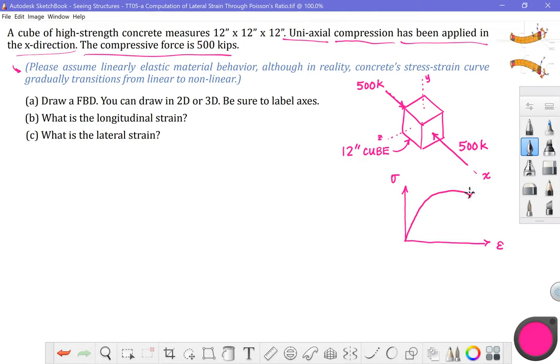something like this. So unreinforced concrete will have a linearly elastic range here at the beginning of the curve. The slope is the modulus of elasticity. And then we have that kind of gradual transition into inelastic behavior. We would not say that this material has the yield point phenomenon or that it possesses a yield point.